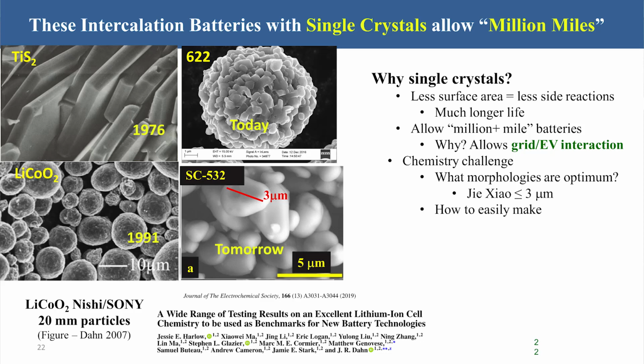And then commercially today we use these meatballs, and it's now been a big push for the last maybe 2 years. Why don't we go back to single crystals? These have less surface area, less reactivity, and they shouldn't crack. The issue with the meatballs is the primary particles expanding in different directions, so it's the meatball itself that cracks rather than the primary particle. So Jeff and others have done studies on these materials. If you don't stress them, he claims you can get the equivalent of 1,000,000 miles if you put them in a car. I should emphasize Jeff is kind of chief scientist for Tesla. So Tesla supports all his work back in Halifax, Nova Scotia.